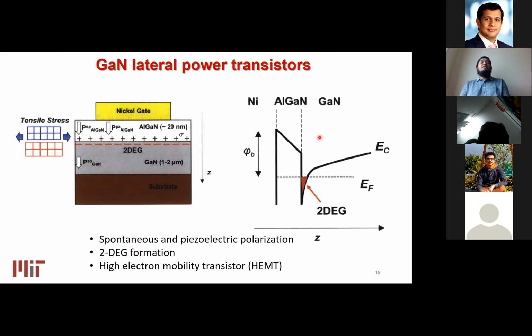On the right-hand side, I'm showing the energy band diagram along this z-axis. We have nickel on the left, and then this aluminum gallium nitride and the gallium nitride. As we can see, because of this piezoelectricity and the spontaneous polarization, a quantum well has been formed right at the interface, where we have a very high mobility carrier concentration that can act as a channel.